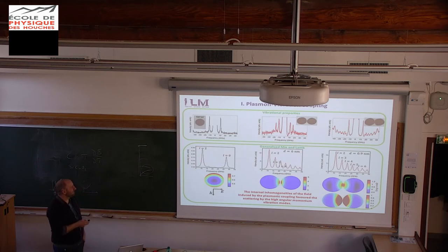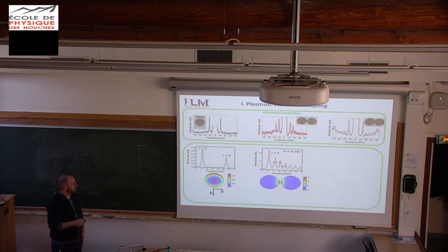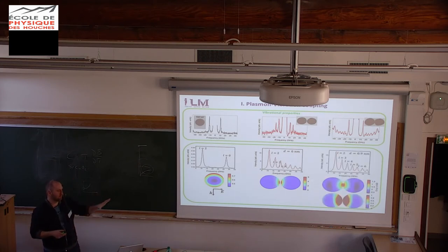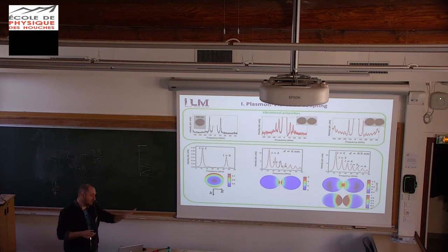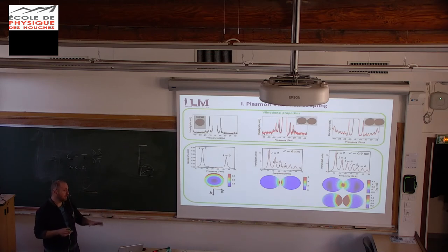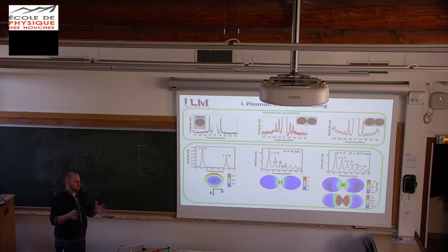It's difficult with this size of nanoparticles to have good imaging to know exactly the gap. What we do is we just measure the optical properties, and we make a modelization of these optical properties, and we make fits, and we say that it's almost 6 nanometers. It's true, we don't really know what the distance is.